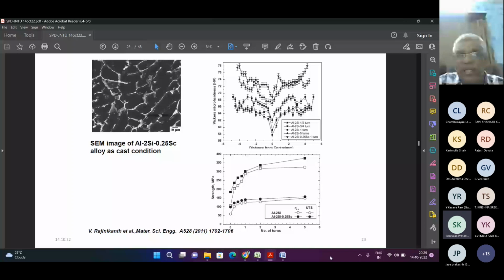We did the Vickers micro hardness test clearly, with different turns like quarter turn, half turn, three-quarter turn, 1 turn, and 5 turns. As I said earlier, after 5 turns there is no further change. If you see very carefully, 1 turn and 5 turns give almost the same properties, 75 to 76 hardness values, and in the center it will be less. Why? Because the strain is taking place at the edges of the sample. The edges are giving more micro hardness compared to the center of the sample.